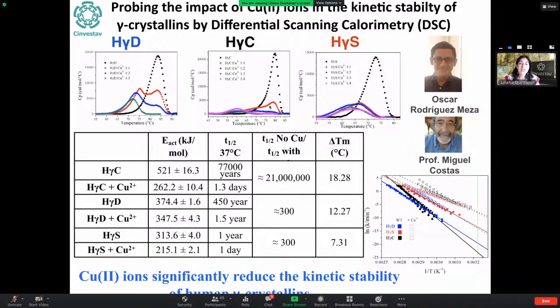So we cannot extract any thermodynamic parameters from this process, but we can get a sense of the kinetic stability of these proteins and calculate a half-life time for these proteins. This is in the order of years for the wild-type protein, but it goes down 2 to 7 orders of magnitude, depending on the protein, when we add the metal ion. So really, copper ions are significantly reducing the kinetic stability of these proteins.